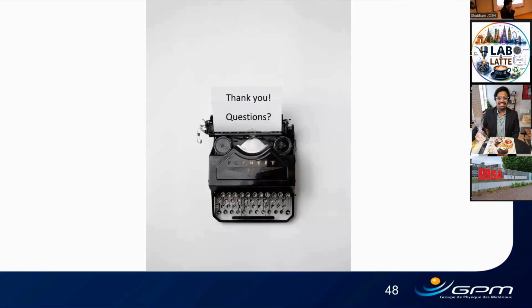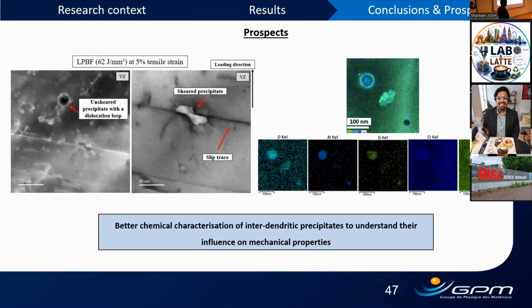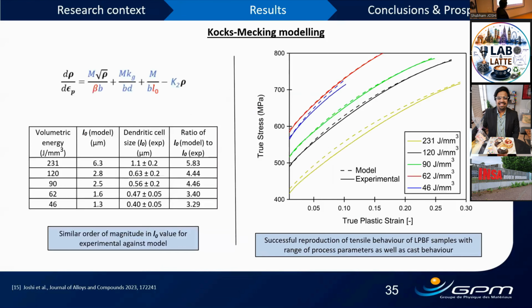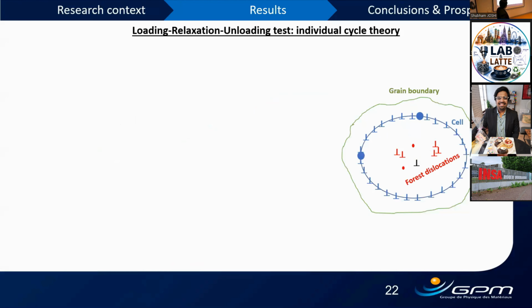Okay, and you said that for each condition you did 3 tests to check the repeatability of your results. Yes. But if I'm not wrong, I think you don't show this in the manuscript or in the presentation. So when you make a tensile test, the 3 tests are always exactly the same? Always. Well, no, not exactly the same, but within a range of 20 to 30 megapascal difference. Yes, but in the mechanical properties that I showed here, we can see the error bars as well.